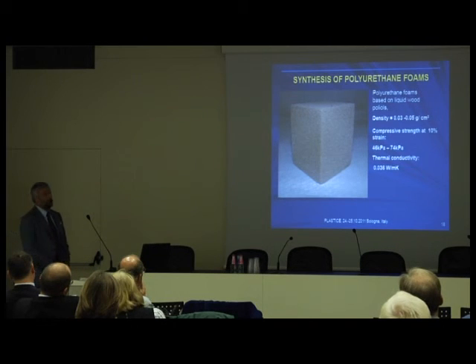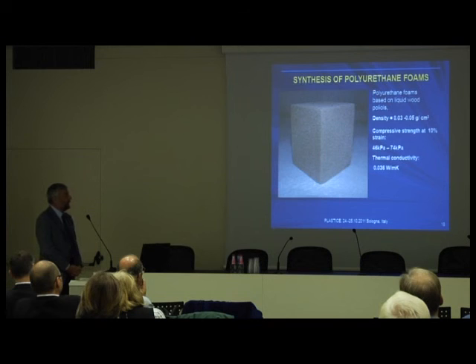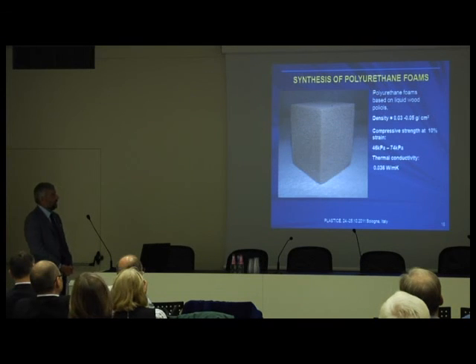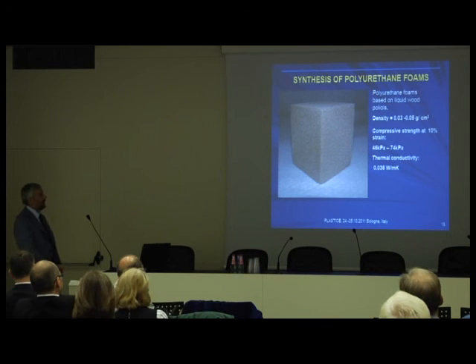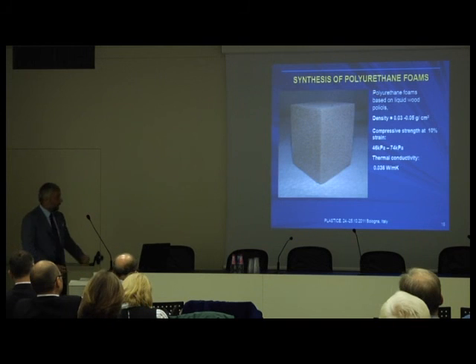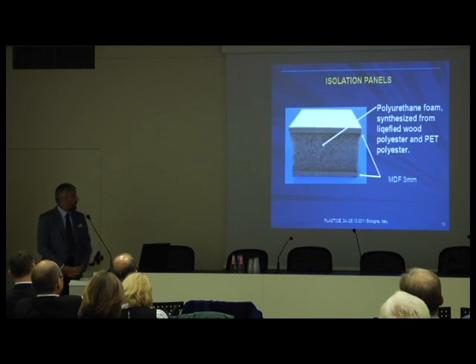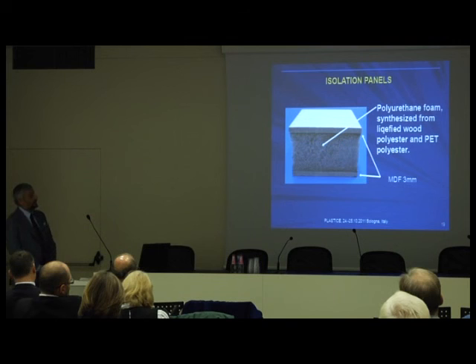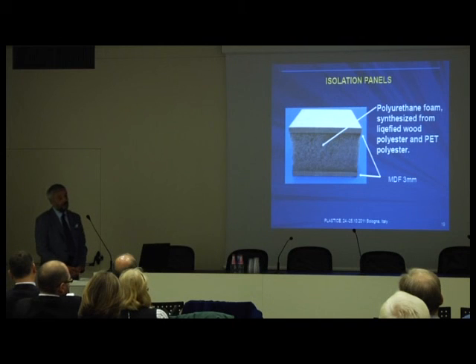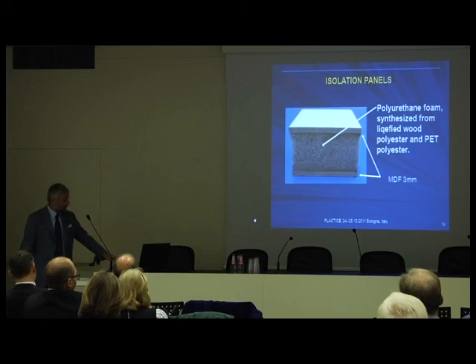The thermal conductivity is in the range of the standard polyurethane foams. The compressive strength is also in the range of these commercial products, and the density is quite favorable. We think that such insulation panels could easily be made on the basis of this polyurethane foam. This is our goal in the next 6 or 9 months.